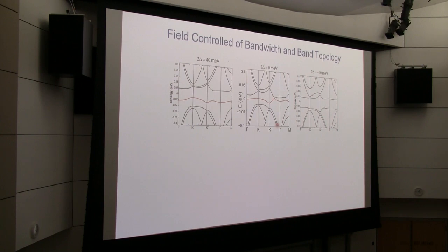So what you find is first you develop a rather narrow Moire band. When you don't apply any electric field, that's the middle plot, you have zero band gap. If you apply, say, a positive electric field, you can open a band gap over here. When the band gap opens, you effectively squeeze the valence band, let's say this red band. So you are changing the bandwidth, and as a result, you change the correlation in the system. At the same time, you can create a band gap with both positive and negative field. If you go through positive field, zero field, and negative field, you see a finite band gap, close it, and open it again. That is a band inversion type of process, where on the two sides, you always have a change of band topology.